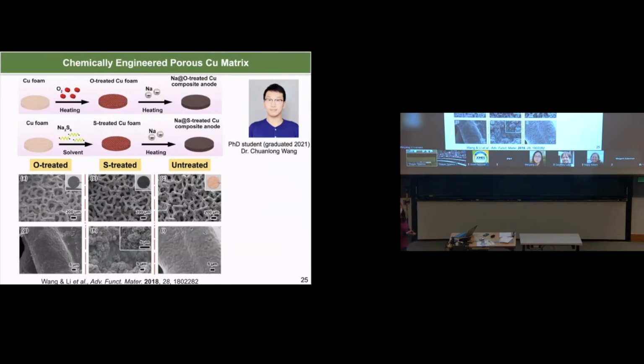First we began to work on some copper-based matrix material, because copper is widely considered a good substrate material for battery anode material. This work was conducted by my prior PhD student who graduated last year, Dr. Wang. Chuanlong found an easy way to functionalize a copper foam, a porous copper substrate, by two different methods. One we call the oxygen-treated copper foam, the other the sulfur-treated copper foam. The treatment is very easy. You just simply oxidize the copper foam in oxygen for about 4 to 5 hours. For the second case, we use a sulfur system to sulfurize the copper foam.